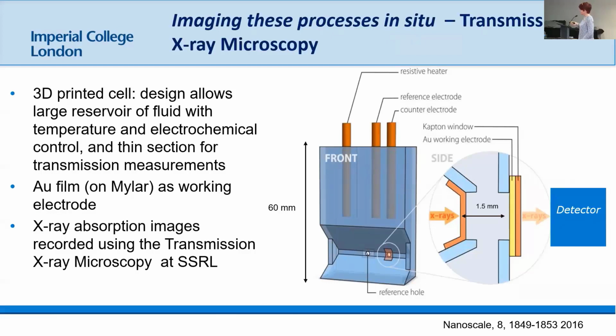So we've got an electrochemical cell here. It's got a bulk electrolyte at the top and flow at the bottom. And then this little narrow window, it's about 1.5 millimeters, because I want my X-rays to be able to get all the way through now. So this is a big constraint on the system, but I can have liquid flowing through and normal electrochemistry.